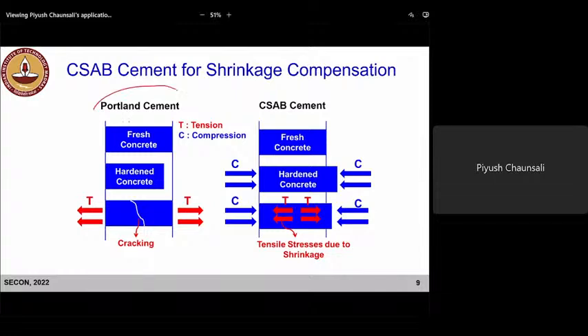So if you look at the Portland cement concrete, for an example, you have a fresh concrete, right? And it's always under restraint. Either you'll have reinforced steel, it will have support, right? Or subgrade, it will be on something. So there is always going to be some restraint. And we know that with time, as it hardens, right, there is going to be shrinkage, drying shrinkage, as you call it. And that drying shrinkage, concrete is shrinking, but restraint is not letting it shrink. So what happens? Concrete is under tension.